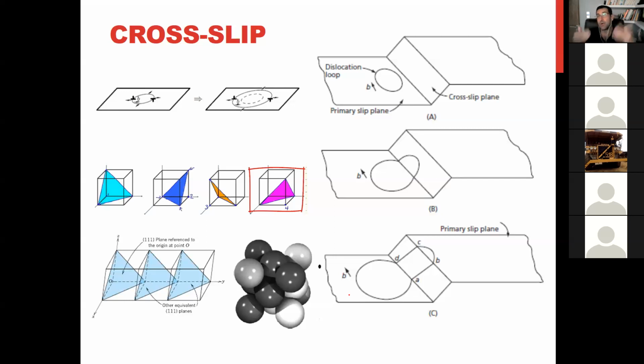Because if you have positive and negative dislocations and they come to each other, they can cancel each other. So this is elimination of dislocations. The density of dislocations must decrease by plastic deformation, not increase. But actually, we see in metals, when we deform a metal, the quantity of dislocations rises. For example, if you have 10^6 dislocations per square centimeter, this will reach 10^14, something like that. So we have some source for generating more dislocations during plastic deformation. So why are dislocations made during plastic deformation?